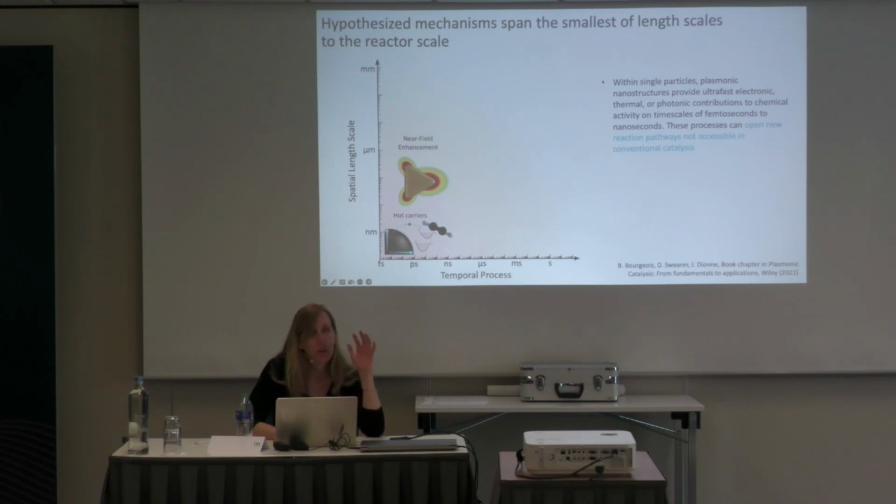As you photo-excite your carriers in the metal, you wind up with an optically excited distribution of carriers that is hotter than the thermal distribution you would expect. So you have your normal Fermi-Dirac distribution, but photons are now exciting more carriers above their current occupancy, and those are hot carriers that can be rapidly injected into either HOMO or LUMO levels or vibrational modes of the adsorbates and molecules in the vicinity.